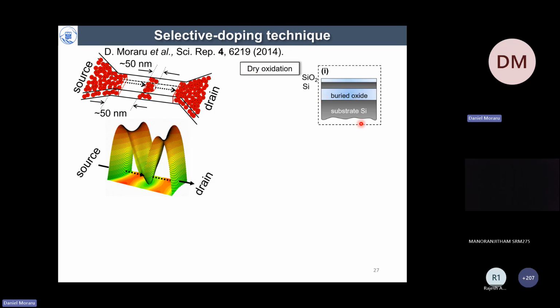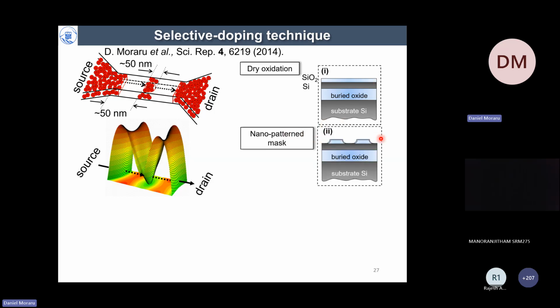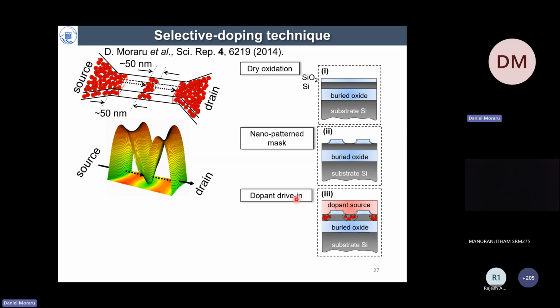So this is a cross-section of our devices, SOI, as I mentioned before. We do a thermal oxidation, a dry oxidation, first. We then nanopattern this mask with an electron beam lithography technique. We open a pocket, a window here, and also windows for source and drain. And then we spin coat the doping source on top of this slightly oxidized surface and drive in the dopants through a thermal diffusion technique in a furnace or a rapid thermal annealing machine. And then the dopants will be introduced only in the desired positions because they cannot penetrate through this oxide mask.